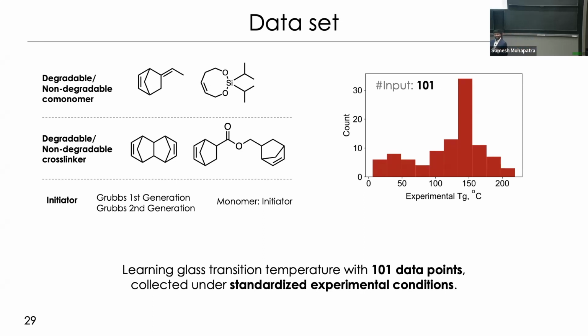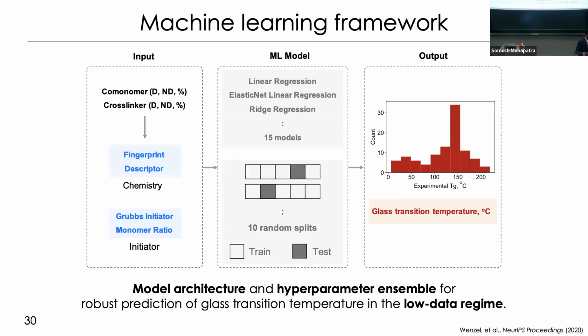After a painstaking experimental synthesis and data acquisition over a whole year or maybe even more, we got to 101 data points. And 101 data points falls in the low data regime. Doing machine learning over just 100 data points, we had to be creative and innovative on how to do that. So we went back to the similar representations because those were really nice, with the comonomer and crosslinker as fingerprints or descriptors and Grubbs initiator as one-hot encoding. If it's Grubbs initiator first, it's a 1, 0. If it's Grubbs initiator second, it's a 0, 1. And the monomer ratio as a continuous number.